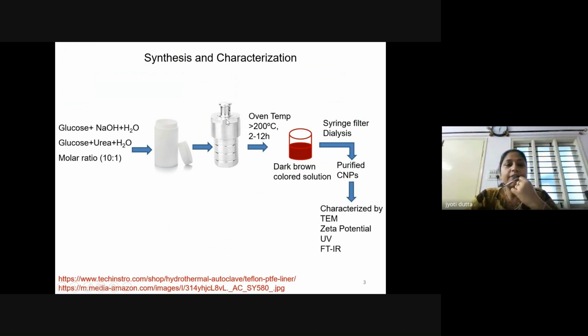Then we have used an autoclave with an oven temperature of more than 200 degrees centigrade. We tried different reaction time periods. So we observed that with different combinations of temperature and time, different sizes of nanoparticles are obtained. The nanoparticle solution which we got after the synthesis is a dark brown colored solution. And we have used syringe filter and dialysis methods for the purification. So no further detailed purification procedure is required for these nanoparticles.